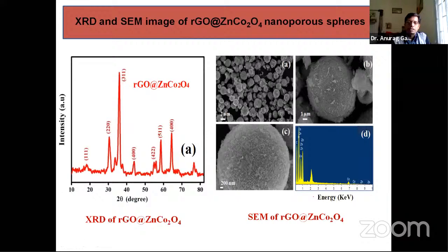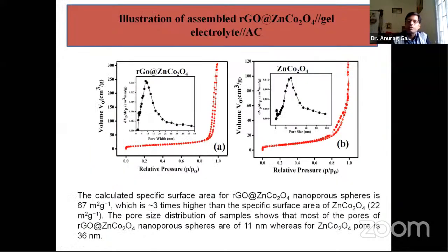Everything has to be tested first through XRD. Then the morphology of the material shows that spherical balls are being formed. That has been checked, and this is the elemental analysis for these nanoporous spheres. Then the BET measurements are performed to see the pore size and the surface area. By measuring all that, we found that the surface area is 67 meters square per gram and the pore size is 11 nanometers. So again, this is in the mesoporous range.